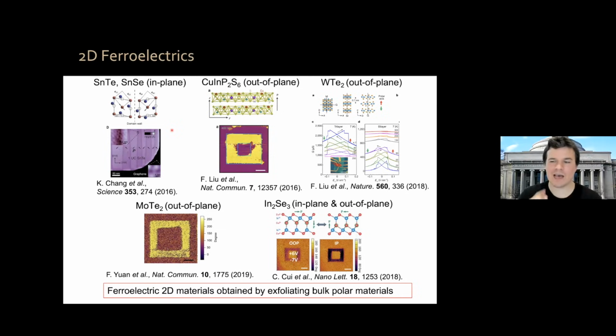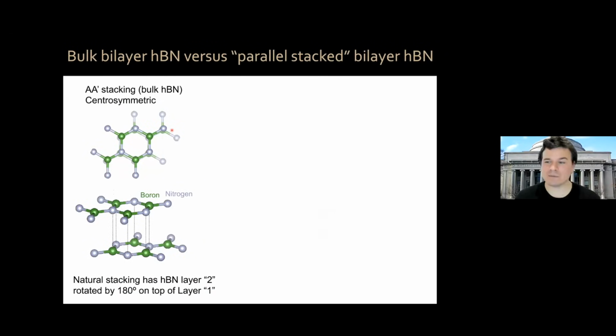By Moiré ferroelectricity, I mean something different. In the same way that graphene is not a superconductor or an insulator, but when you twist it, when you put it on top of each other and you make a Moiré system, you can have a correlated insulator or superconductor. Now we can obtain ferroelectricity out of a material that in the bulk is not ferroelectric, okay? So the system that we chose to do this, there are many more potentially, is hexagonal boron nitride. Hexagonal boron nitride is a honeycomb lattice also, where you alternate boron and nitrogen atoms. It's like graphene where the A and B sublattices are now boron and nitrogen atoms, okay? So now they're chemically distinct.